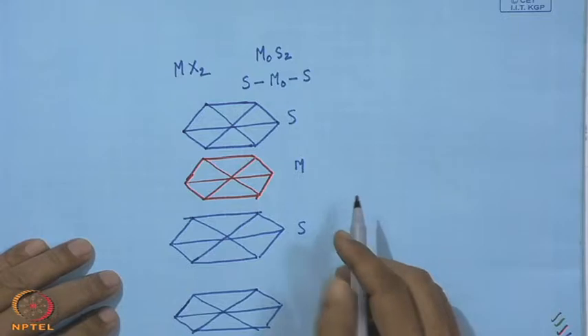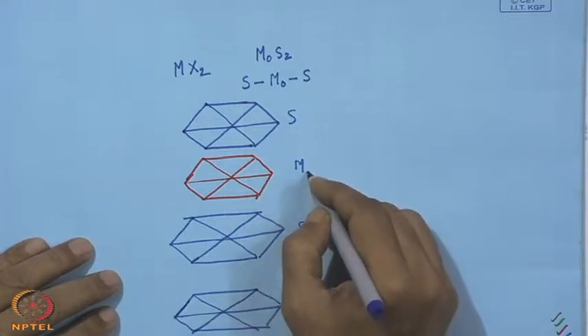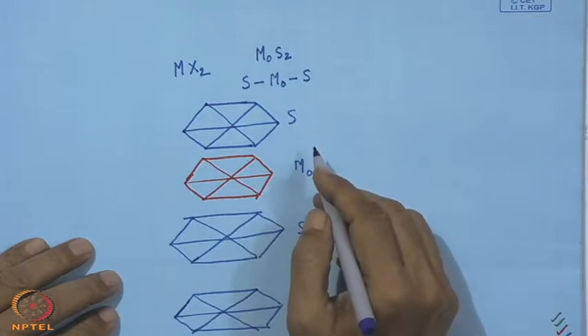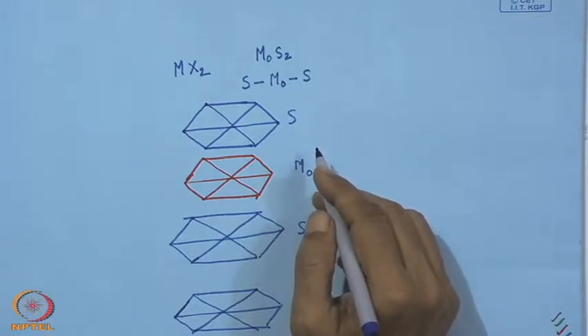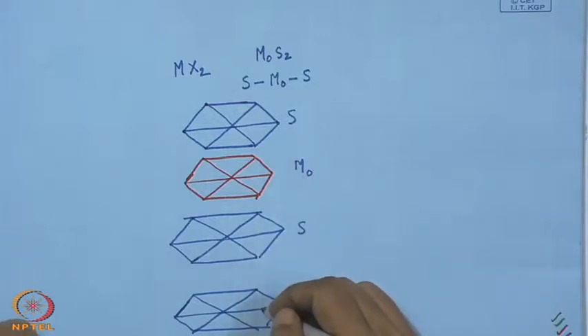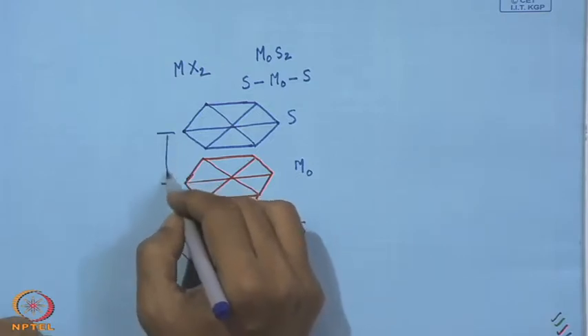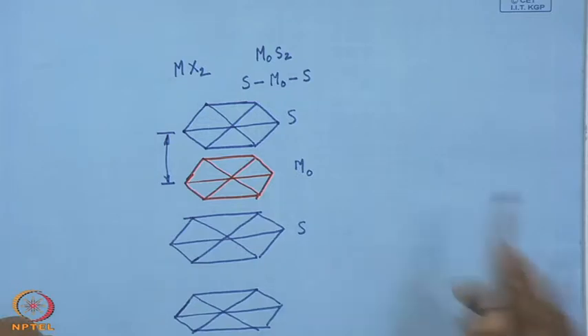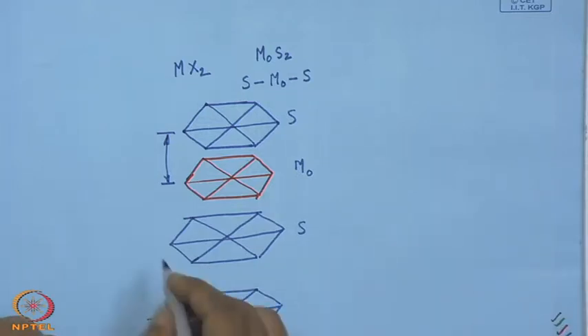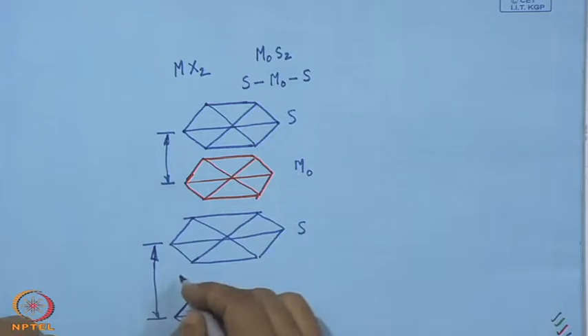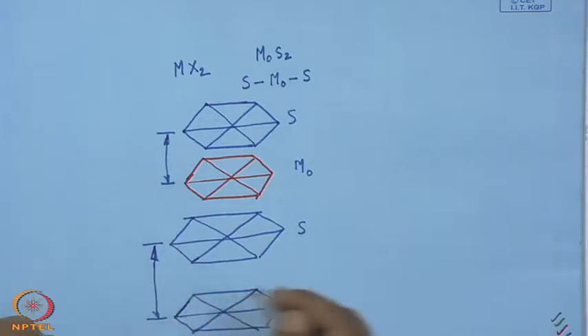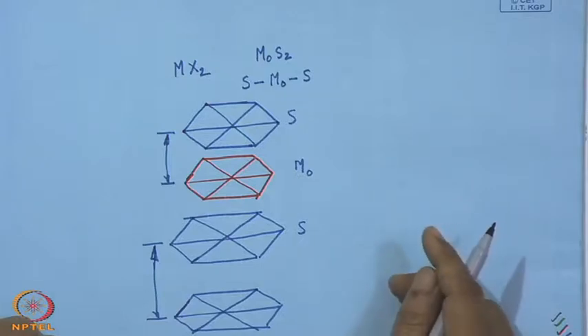So, what we find normally is that the bond between this molybdenum and sulfur is a covalent bond, that is very strong. However, the bond between this sulfur and this adjacent sulfur, which is from another MoS2 set, is rather weak, and this interatomic distance is more than the interatomic distance between two sulfur planes within a set. So, this distance is high compared to this distance, and the force between these planes is a very weak force, that is the van der Waals force of attraction.